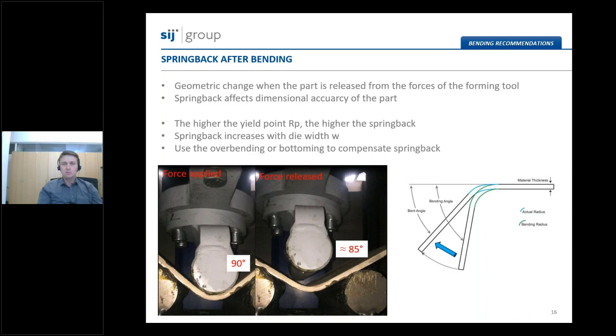Some basic background about the spring back was already explained at the beginning of this webinar. Spring back is a geometric change when the part is released from the forces of the forming tool. And this phenomenon always appears when we are doing the bending process on metallic material. So it is seen during the V-die bending and also during the air bending operation. Spring back is measured in angular degrees. The higher the mechanical properties, in particular the yield strength, the higher the spring back after the bending. What it means? It means that conventional S355 grade has a lower value of spring back than, let's say, SIMAXX 1000 grade.